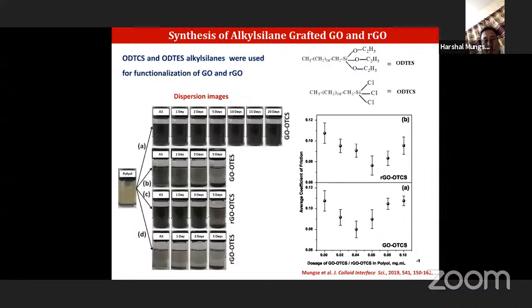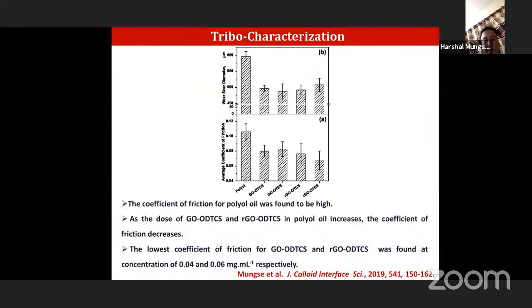Then we checked the tribological properties of this material. You can see in the graph at 0.06 concentration or 0.04 concentration, which are the optimized concentrations, there is significant reduction in the friction and significant reduction in the wear as compared to neat oil or neat lube base oil. By this way we can reduce friction and wear. Here also, if I functionalize this material with ODTCS or ODTES, the wear scar diameter is near about 550 in the case of neat oil. But when I use that functionalized material as an additive, you can see the reduction in the friction and wear in this graph.